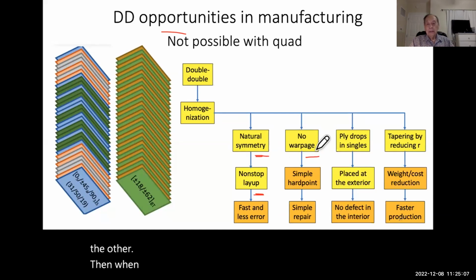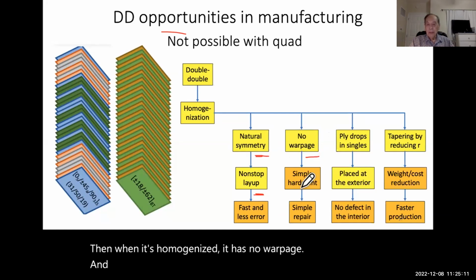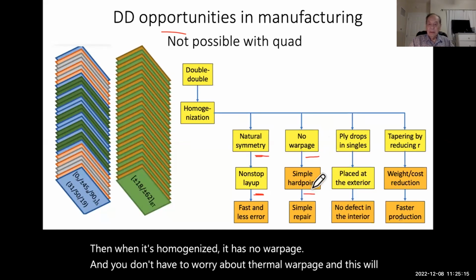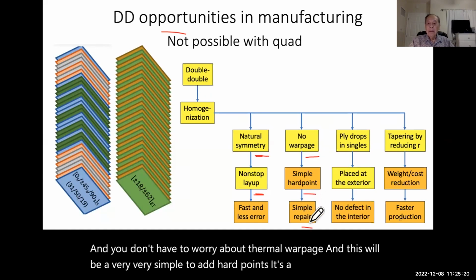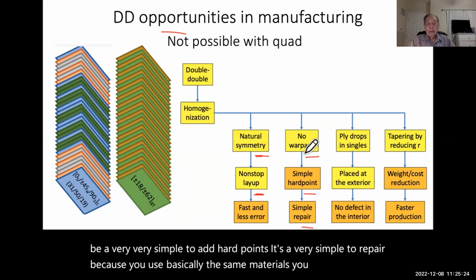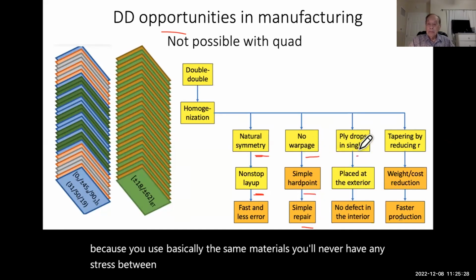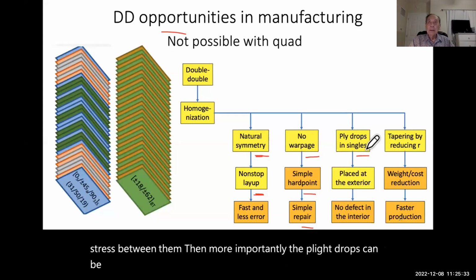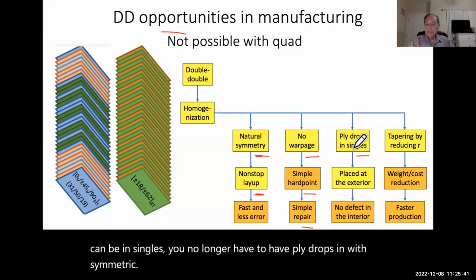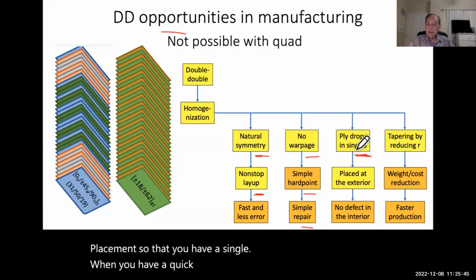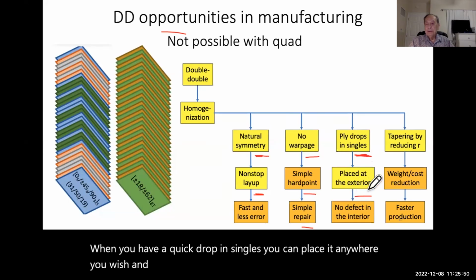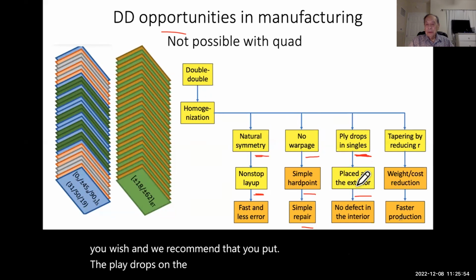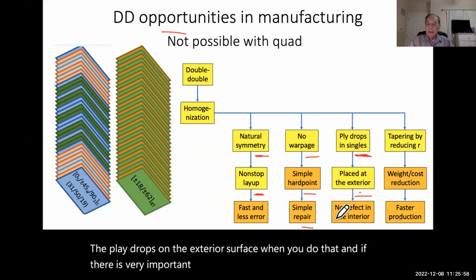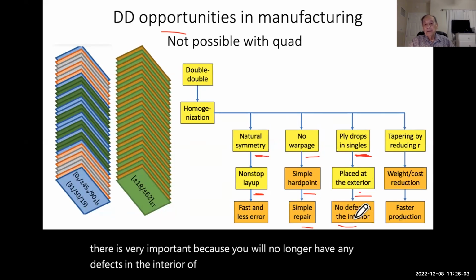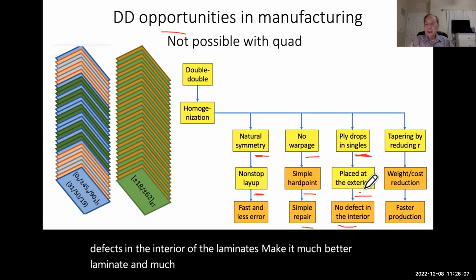Then, when it's homogenized, it has no warpage. And you don't have to worry about thermal warpage. And this will be very, very simple to add hard points. It's very simple to repair because you use basically the same materials. You never have any stress between them. Then, more importantly, the ply drops can be in singles. You no longer have to have ply drops with symmetric placement, so that you have a single. When you have a ply drop in singles, you can place it anywhere you wish. And we recommend that you put the ply drops on the exterior surface. When you do that, and it is very important, you will no longer have any defects in the interior of the laminates, making a much better laminate, much stronger and less likely to delaminate.